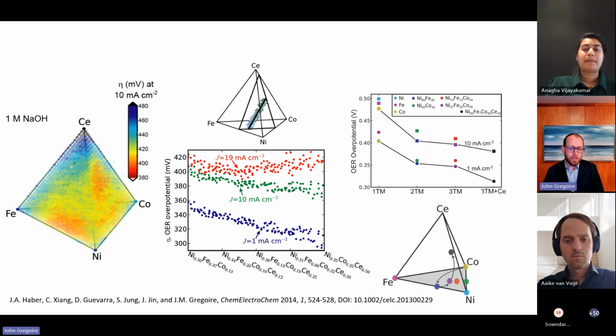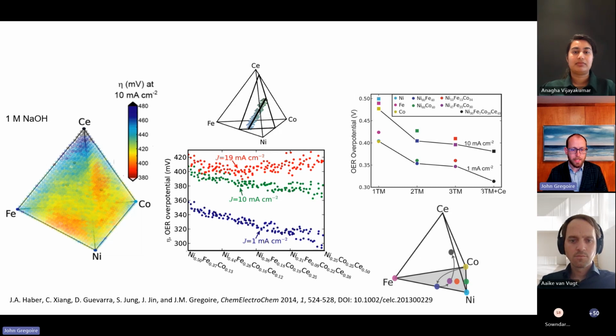And if you ask, well, what's the best catalyst in this space? Well, it depends on what current density you're operating at, because at high current density, it's here. And at low current density, it's very much these cerium-rich compositions, which was surprising to us because cerium oxide by itself has no notable activity for oxygen evolution. And yeah, sorry, I forgot to mention this is in alkaline conditions, 1 molar sodium hydroxide.